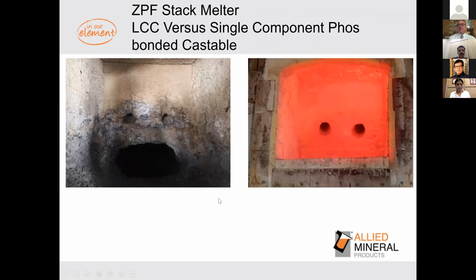So it's nice to do things in the lab to come up with things, but always the proof of any product is how does it work in the field. On the left is an aluminum furnace that had the low cement type castable. This furnace ran for 5 years, so it did an excellent job. But we were always in a continuous improvement mode. So that furnace, when it was relined, was done with a single component castable. And you can see here, after many months of operation, you do not see buildup in the furnace at all with a single component.